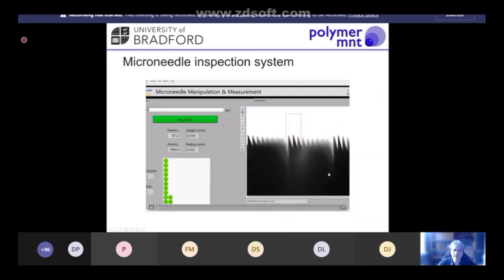I can actually show the system in use here. So here you can see we're moving around from microneedle tip to microneedle tip in the array. And at each point, we're getting a measurement of the height of the microneedle and the tip radius here in microns of each microneedle in the array. So purely using the fact that the microscope objective has a very low depth of field, which allows us to individually identify each microneedle in this array. And by traversing from needle to needle, we're able to build up a full representation of the microneedle quality within the array. So these dots here, green means that the quality is okay in terms of the height and the radius of the needle.